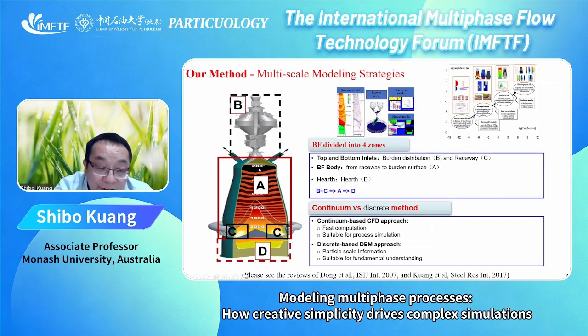And the phenomena inside the blast furnace are very complicated. We have particles, liquid, powder, gas, and many reactions happening under high temperature and high pressure. It's very difficult to use a single method to simulate this system. So in our study, we divided this reactor into 4 regions, and we developed a submodel to simulate each region, and these models can be used individually or combined together in an integrated way.